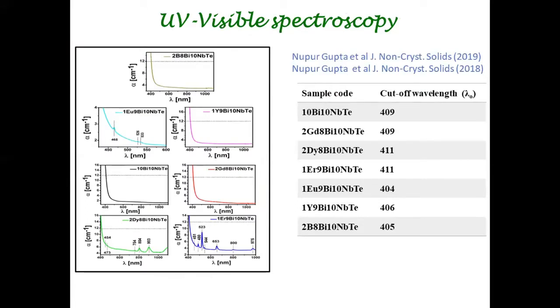So we record their UV visible spectra to see where the absorption bands take place. And we should excite the sample near these absorption edges when we are doing photoluminescence spectroscopy. The edge is around 400 nanometers for almost all the samples. So below 400 nanometers, the absorption will be very high. Typically we would like to expose the sample to wavelengths where the absorption is high, and the sample should emit light where its absorption is less. That is of course true in the case of europium and erbium doped samples.